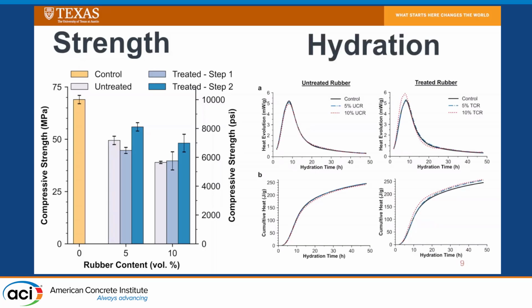We were also concerned about hydration kinetics because we are exposing these rubbers to various chemicals. And what we can see here is that when we look at hydration kinetics, there's really no big change, right? So that is good.